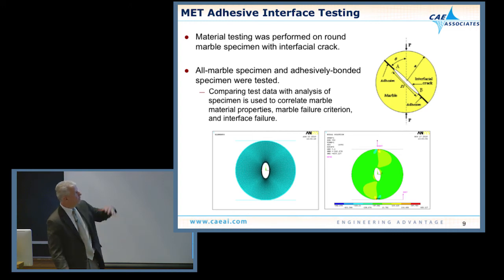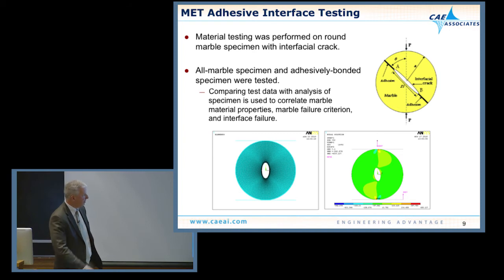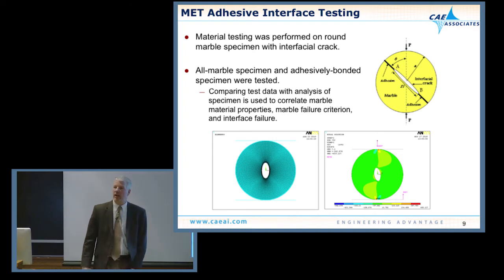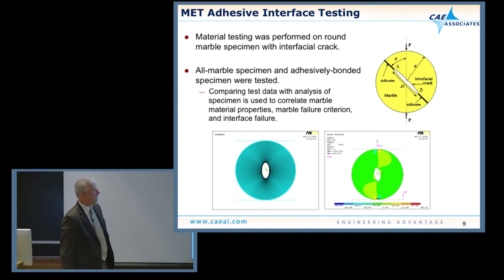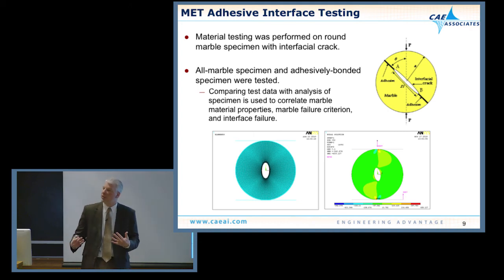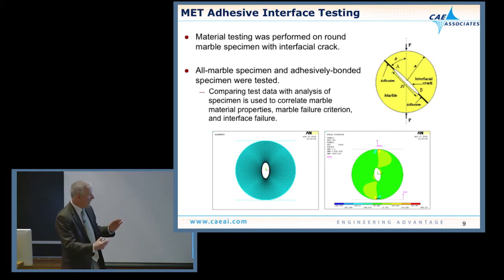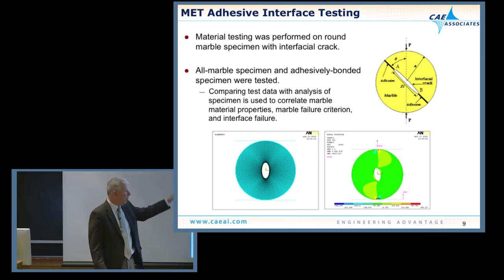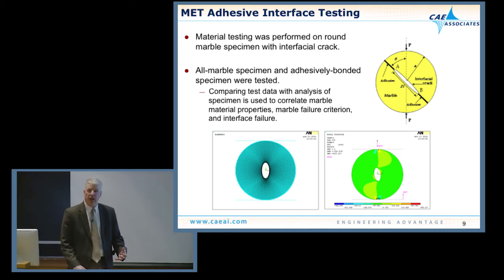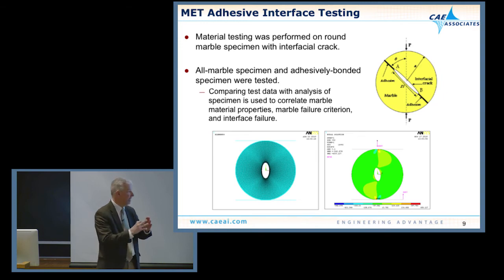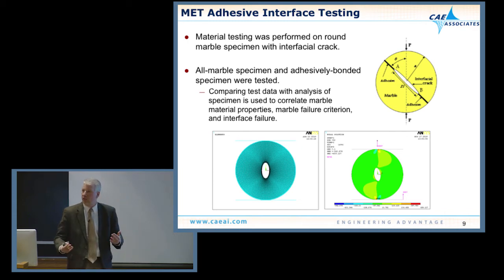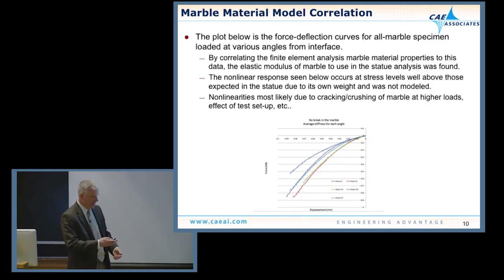So everything looked great. So Carolyn showed you the fracture mechanics test specimen, and we created a finite element model of it, and we can run and apply the loads that are basically putting this thing in compression at various angles, and it's a numerical procedure, so we can run this a million times if we want to get all the different angles and get the response and see what happens. And they started with just all marble with a hole in it, with this oblong fracture flaw in there. So that's great because we can use that to correlate the marble material properties that we used in Pat's models. And then they did some specimens that were glued together, and in the specimens that were glued together, that's the delamination singularity. We can look at the failure stress when it delaminates, and then we'll have failure information for both the marble and the delamination. So everything looked great.